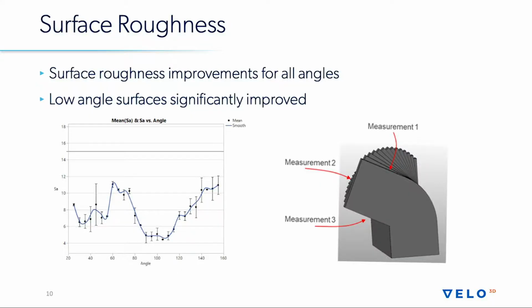These are surface finishes that we're measuring, so statistical significance on actual measurements with Sa. We measure Sa because we consider it to be a better measurement of surface finish, because with Ra it depends on which direction you're scanning. If you scan across layers, you can get a much different Ra than if you scan with layers. So Sa somewhat accounts for that, and at least you won't be surprised by the part you get out of the machine at the end of the day if this is the data that you get up front.